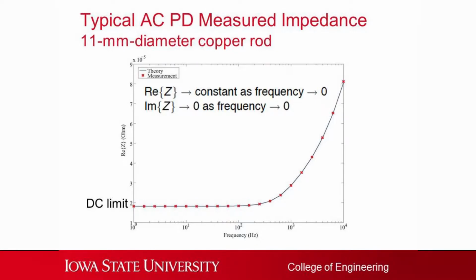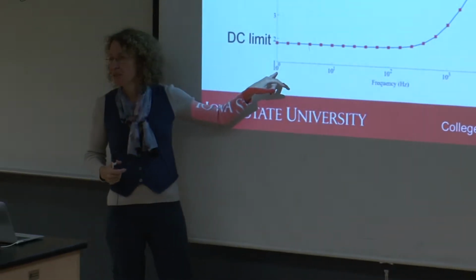Okay, now this is a plot of taking one of those 4-point probes and putting it down on a copper rod. Okay, so we're putting 4 points along the side of a copper rod. It's 11 millimeters in diameter. What we find as we change frequency, so down here is 1 hertz. As we increase that, this is 10 kilohertz up here.